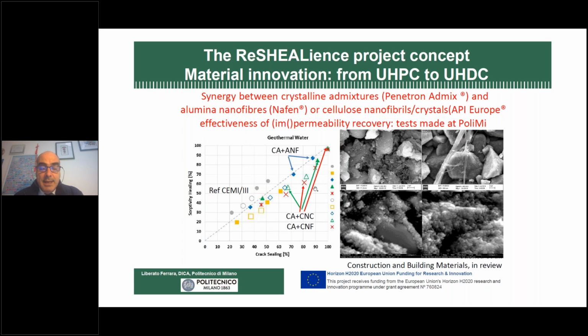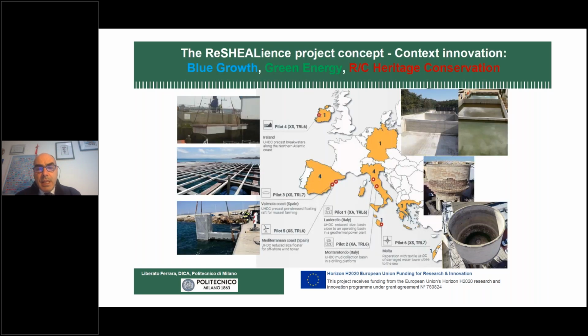You can see that the dots representing this material, the blue, the green, and the red, in all cases, we had the better self-healing and the better recovery of impermeability versus water capillary absorption. So what we did with the materials that we developed, as I said, it's not a unique material. Each material was designed with specific reference to the pilot and to the conditions that it had to experience.